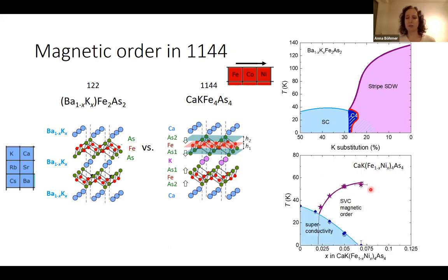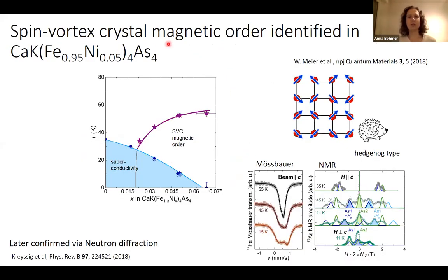The phase diagram we found upon nickel substitution indeed shows some magnetic order. What we find is the suppression of superconductivity. One might think half a superconducting dome, maybe, and we find a magnetic phase coming up here. This magnetic phase was identified to be not the stripe type order that comes to our mind when we think of iron-based materials, but what's called spin vortex crystal magnetic order. That was also mentioned yesterday. In the iron plane, the magnetic moments form this non-collinear pattern, and when you go around an iron plaquette, the orientation winds. So that's where this vorticity comes from, and the name. There are actually two types, and this one with some all-in, all-out structure we named hedgehog type, for some visual.